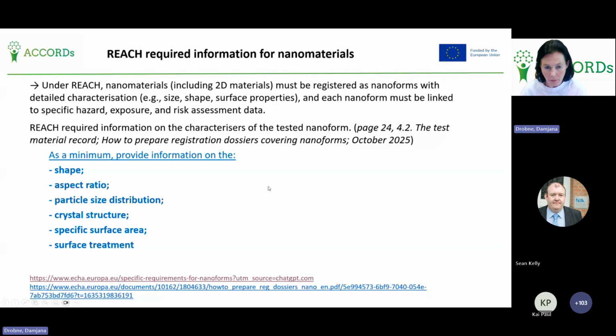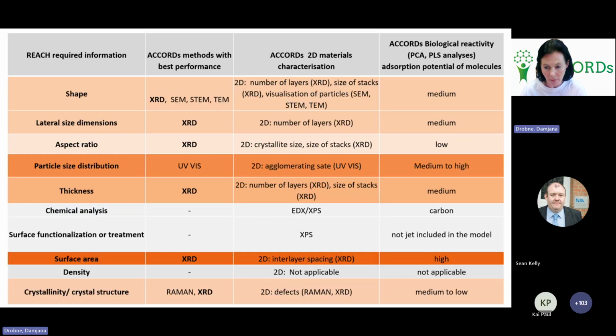When we look at the REACH requirement and the REACH information for nanomaterials, which is shape, aspect ratio, particle size distribution, crystallinity, surface area, and surface treatment, and then translate these into our characteristics, we get this. So when it comes to shape, the methods that perform best are XRD and then electron microscopy. We cannot talk about shape in case of 2D materials. We talk about number of layers, also size of stacks, perhaps also visualization of particles.